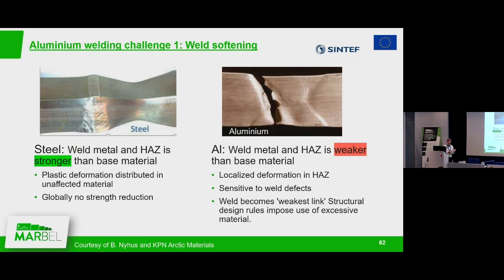In aluminium, in opposite, we have different problems. In this aluminium, which is a precipitation hardened alloy, the weld actually destroys the properties of the material. So according to current standards, you have to have double the material you would otherwise have needed. So you have to add double the mass. Aluminium is approximately one third of the density of steel, but a little bit softer. In this case, you will lose all the benefits of using aluminium if you don't do anything about it.